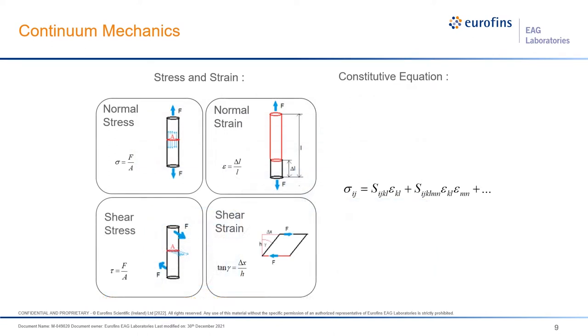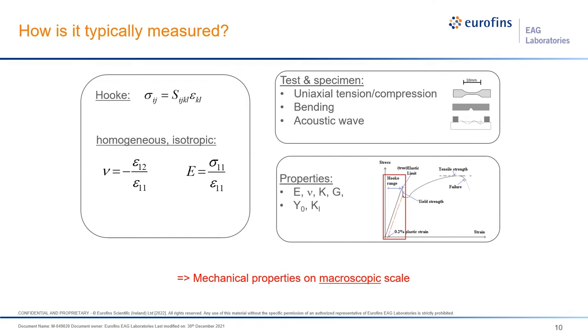How do we do this? It starts with a theoretical foundation in continuum mechanics. Forces and deformations are expressed in terms of stresses and strains. We write down the constitutive equation linking those both — typically developed as a Taylor expansion in tensorial notation, which is quite a complex structure. It's typically truncated after the first term. With the elastic tensor having 81 independent components, it's still very unwieldy. For many mechanical characterization problems, a significant simplification is made by limiting to homogeneous isotropic materials, leaving only two elastic constants: the Poisson's ratio and the Young's modulus.